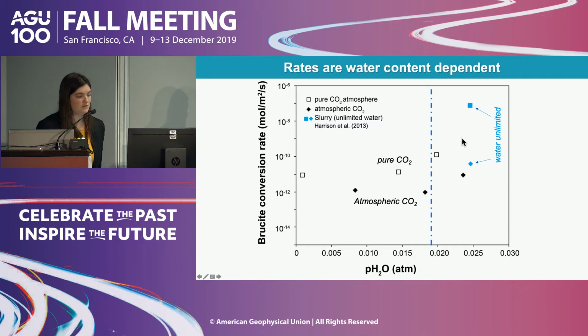And notably, the two blue points here are the same reactions but occurring in water unlimited conditions. So in batch reactors where we have a small amount of solid, a large amount of fluid. And what you notice is, particularly for the atmospheric CO2 experiments, our rates at 100% humidity are not really that far off what we observe in water unlimited conditions. Granted, there's uncertainty with the way we can calculate these rates. But nevertheless, we have rates that are not far off water unlimited conditions. And so ideally what we'd like to do is better constrain these reaction rates, particularly above this threshold, and hopefully incorporate these more mechanistically into our reactive transport models.